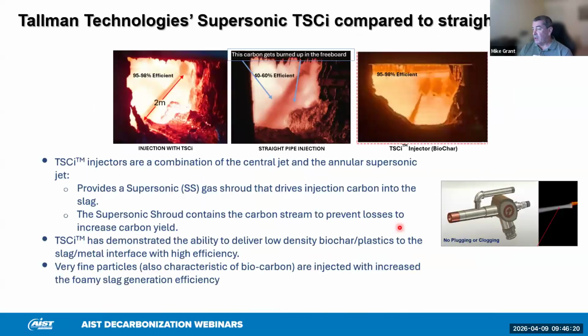There are companies now working on improving the efficiency. Tallman Technologies is an example. They use a supersonic shroud to kind of encase the stream, and they've gone from about 40 to 60% efficient up to about 95 or greater. And this even helps for biocarbon injection. Biocarbon is notoriously bad, low density, very hard to inject. You lose a lot more in the freeboard. Apparently, this also works very well with biochar. So there are companies out there working on this.